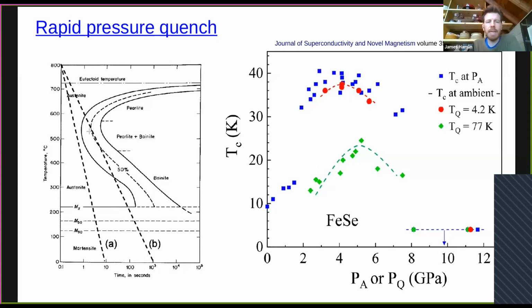And so if you want to avoid that conversion, you have to quench the sample very rapidly along one of these dashed lines. And you can see that there's actually a temperature range where the conversion happens most rapidly. It doesn't continue to occur more rapidly at higher temperature. This may be slightly non-intuitive. And so what Paul Chu has done is he's created a system that allows him to very rapidly change the pressure. So this is kind of the pressure analog of the approach to steel here.